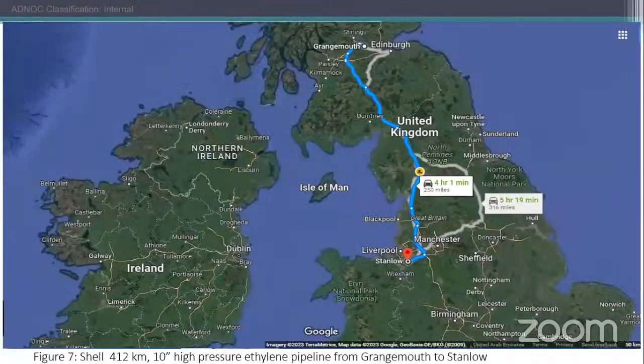Now, in 1992, Shell constructed a pipeline, about 412 kilometers long, 10 inches in diameter, a high pressure ethylene pipeline from Grangemouth to Stanlow. Then in 1994, Shell conducted an ILI, an inline inspection, with an intelligent pig. You introduce an intelligent pig that goes through the line, checking for possible defects, possible loss of metal wall in the pipeline, to know the areas where you have corrosion going on.